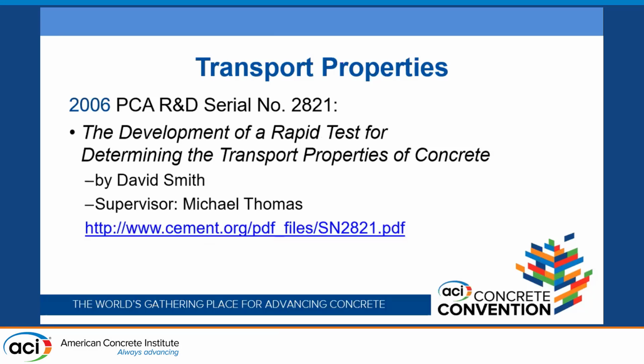Moving on to some other topics that you may be aware of Michael working on. One of the first studies on rapid tests for transport properties of concrete was conducted in the mid-2000s at UNB with one of his students, David Smith. And this test program studied relationships between RCP and resistivity measurements. It's one of the first papers published. Now there are ASTM tests on this, but it was found that there's a good correlation between the rate of chlorides through the RCP and through conductivity tests. So this is a good start to getting more field data available versus laboratory data and correlating the two.